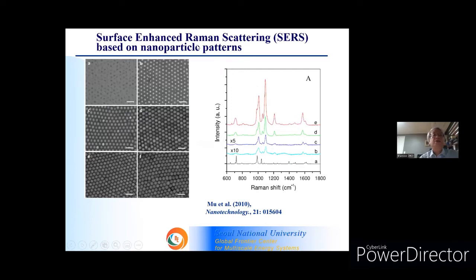Surface enhanced Raman scattering is a powerful tool to detect molecules very accurately, even at the single molecular level, by exploiting the great field enhancement from these metal nanostructures. Depending on how you arrange these metal nanostructures, you can increase the Raman signal significantly.